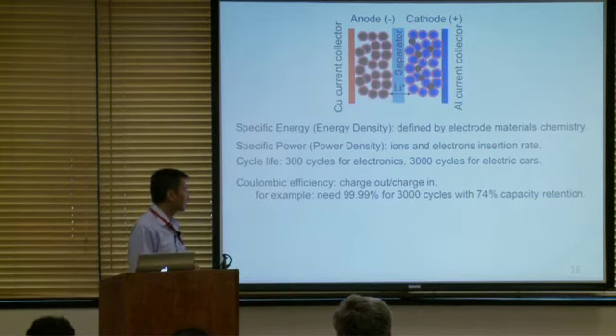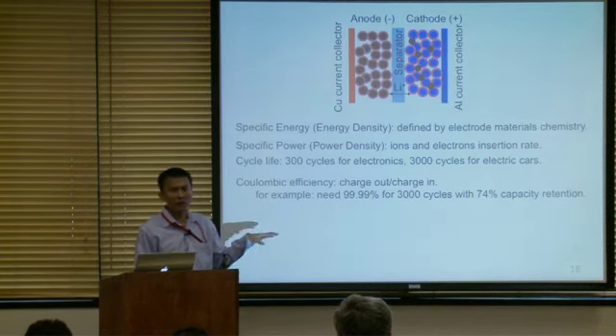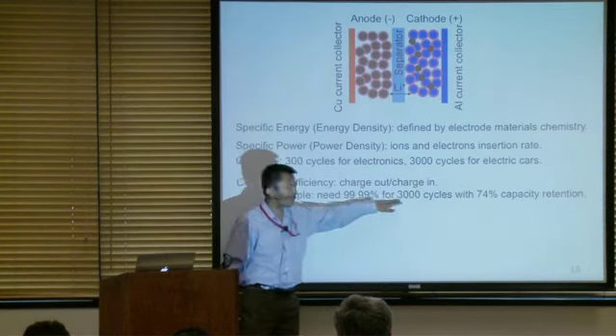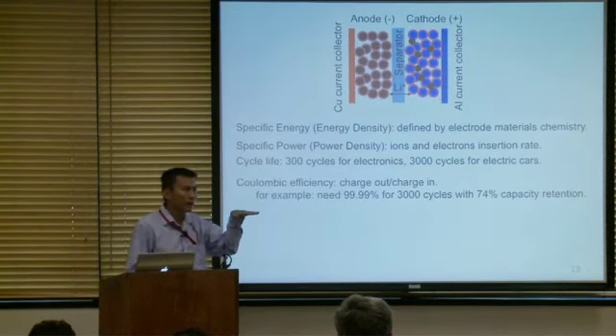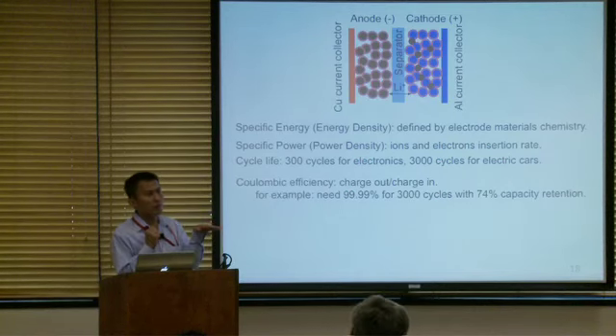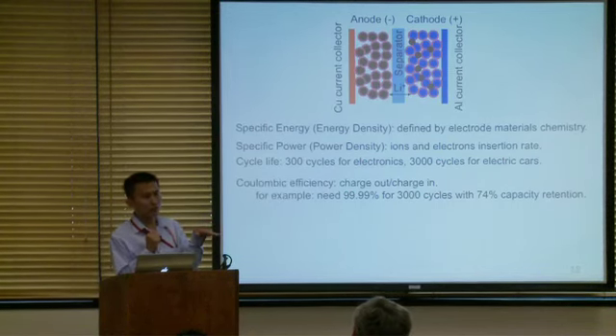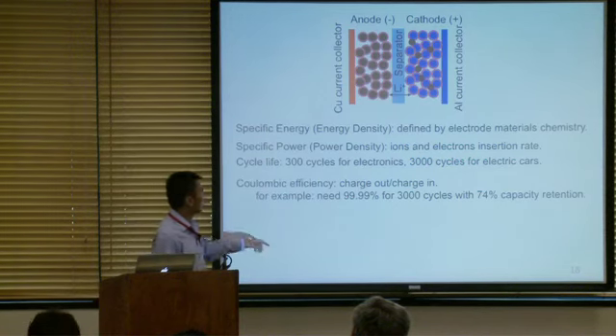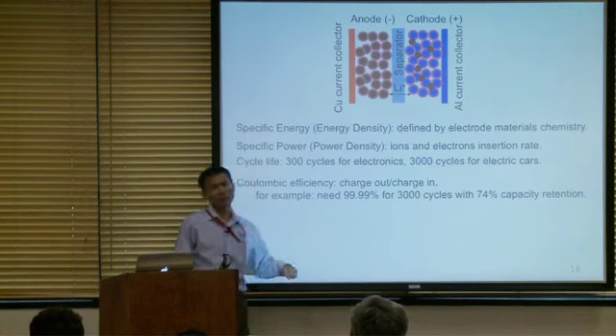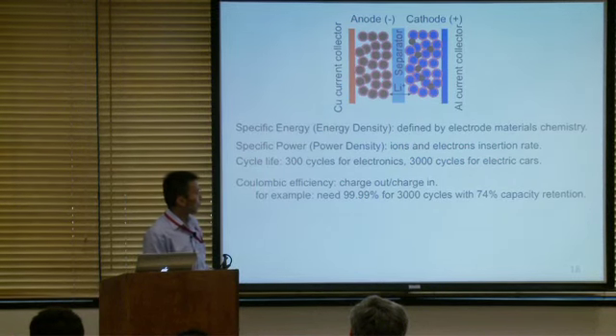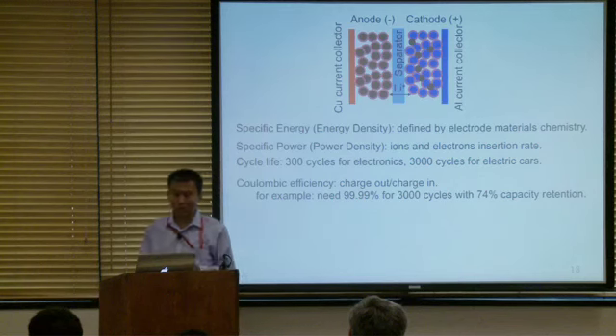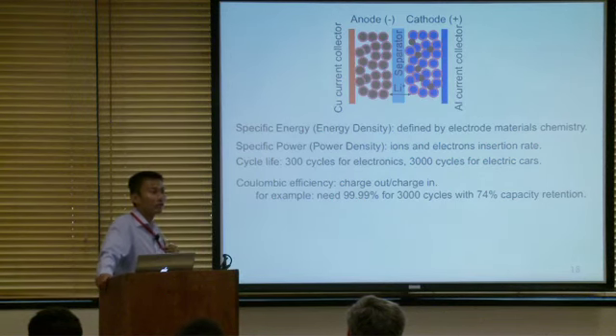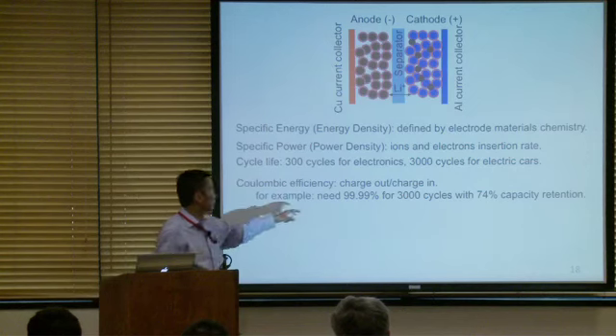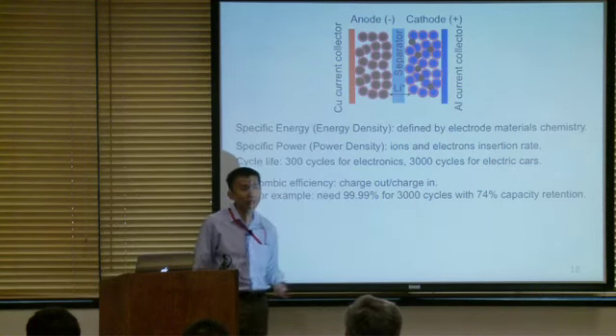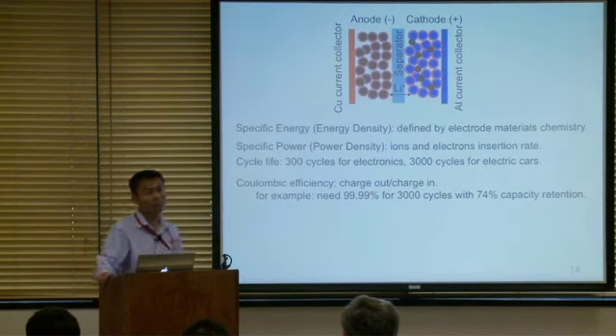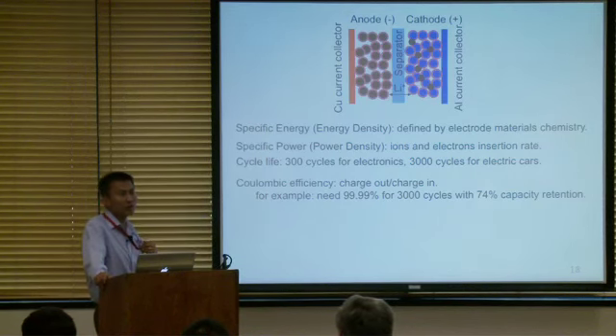Why is that important? Because if you want car battery applications, you need 3,000 cycles. Each time you lose 1 electron, that often means you lose 1 lithium ion too. There's a side chemical reaction. You need 99.99% Coulomb efficiency. Otherwise, after 3,000 cycles, you only have 74% of the initial capacity, the energy remaining. So this is not trivial. How do you get 99.99? Looks like just a purely engineering problem. No, it's not purely engineering. There's a lot of science issues you need to address.